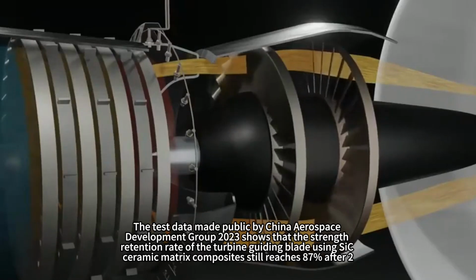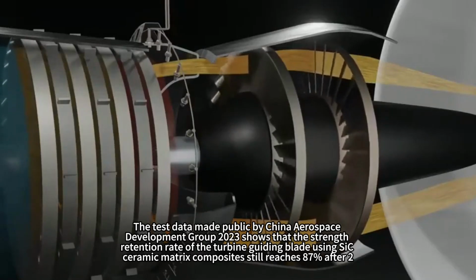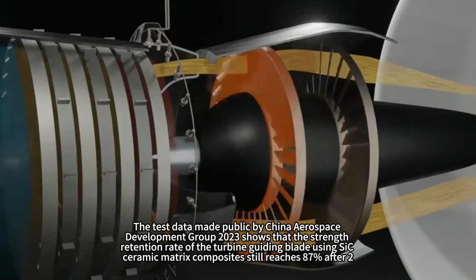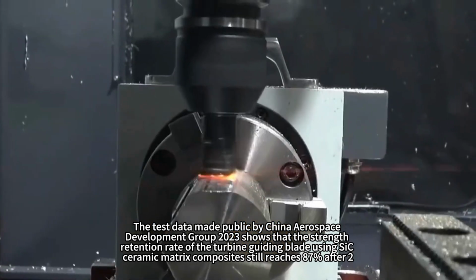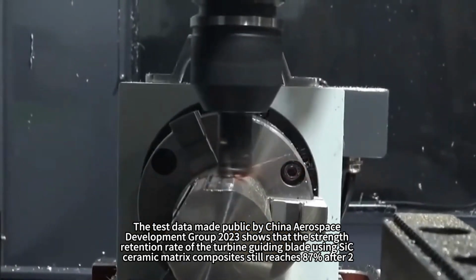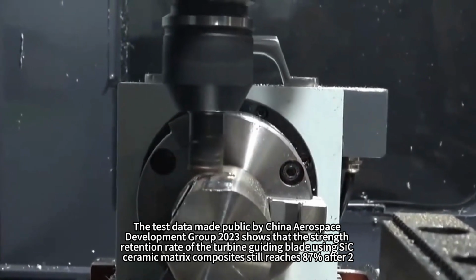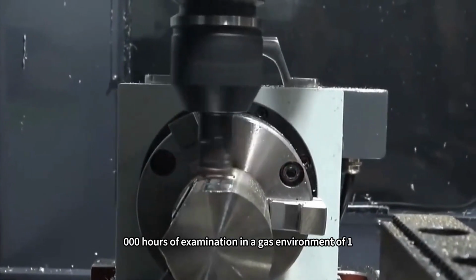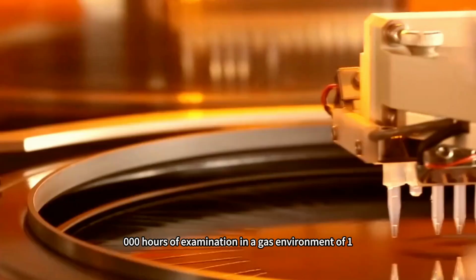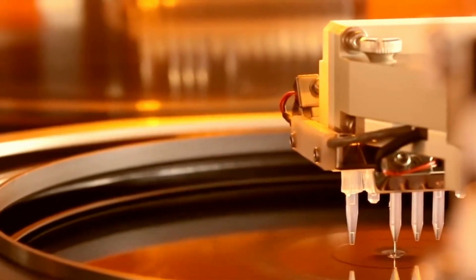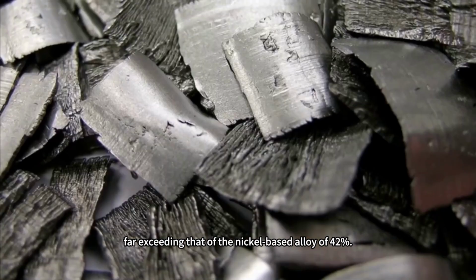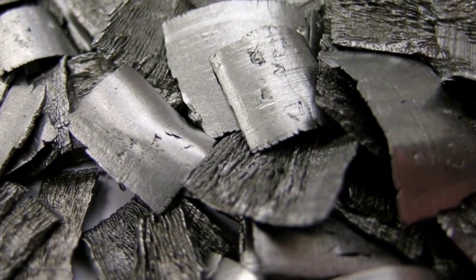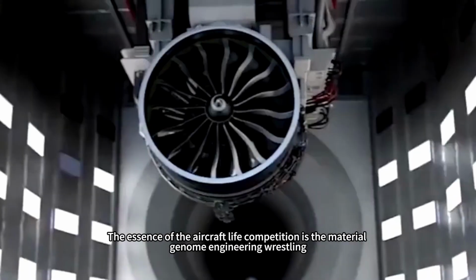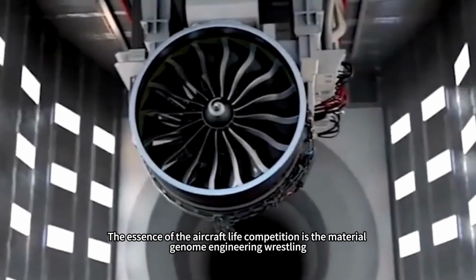The test data made public by China Aerospace Development Group in 2023 shows that the strength retention rate of the turbine guiding blade using SiC ceramic matrix composites still reaches 87% after 2,000 hours of examination in a gas environment of 1,350 degrees C, far exceeding that of the nickel-based alloy at 42%. The essence of the aircraft life competition is material genome engineering wrestling.